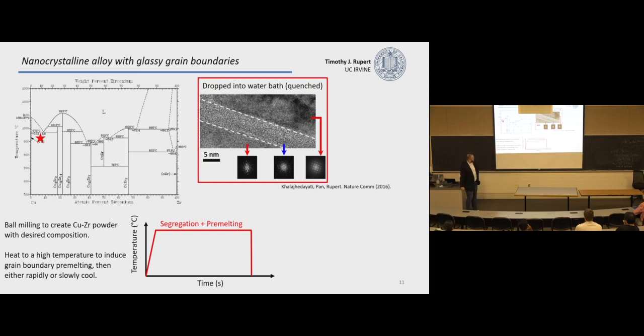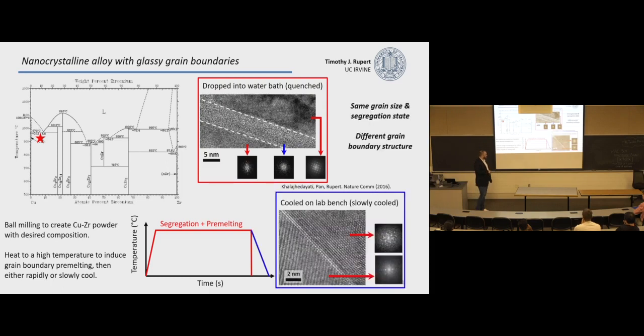The reason this is nice is that we can go and redo that same experiment. So heat it up, allow for segregation and pre-melting. But the whole concept here is that this amorphous grain boundary is a high temperature structure, and we had to freeze it in. So we can just do that cooling step a little bit differently, and rather than quickly cooling it, slowly cool it down. So the same thermal history, same grain size, you still have zirconium at the boundaries, but when we do the TEM, we never find these amorphous films. We only see these boring ordered grain boundaries. So grain 1, grain 2, relatively ordered grain boundary there. And what that does is that gives us two materials that are the same in every way except for their grain boundary structure.